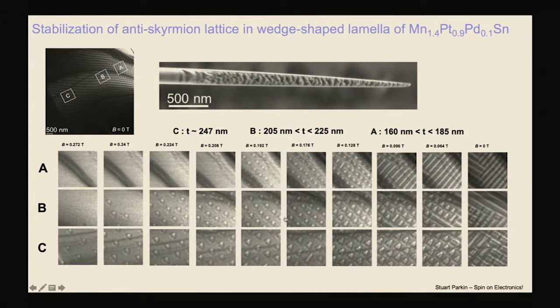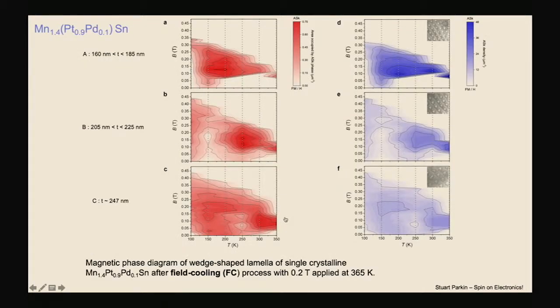And you can see here is that wedged lamella, and we're going to take 3 regions with different thicknesses, A, B, C, and as we vary the thickness from the thinnest A to the thickest, and we look at the skyrmionic antiskyrmion we see as a function of magnetic field, you can see distinct differences depending upon the thickness of this material. So I want to come back to that. And then we can map out the whole phase diagram, the field and temperature dependence at different thicknesses. And the most important point is that we see that there's a wide stability region of antiskyrmions independent of the thickness.